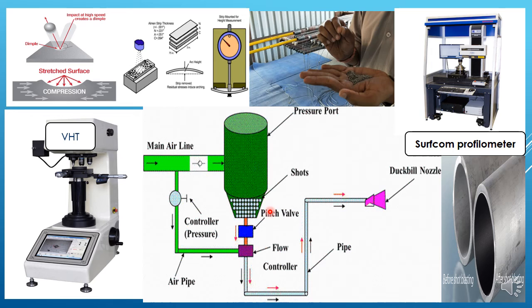How much this shot peening has had an effect we can verify by several tests like the Almen strip test. This test is done locally on the spot. The intensity of the impact can be identified from this test. The treated convex surface is measured for the degree of curvature of intensity. Three Almen strips of variable thickness are kept inside the designated box or fixture tubes, and the strips can be thicker to thinner. It gives 20 to 50 micron of indentation, which can be measured with a dial gauge.